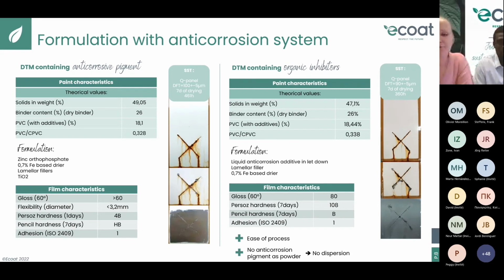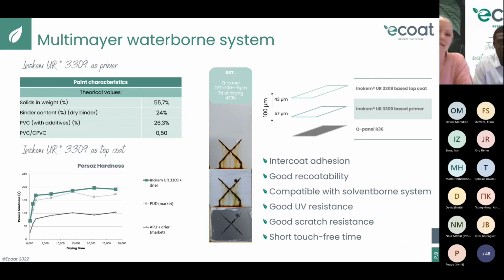These are for the direct to metal coating, but you can also use 3309 in a multi-layer system. Indeed, it is possible to use 3309 in primer or in top coat. Primer is a good option thanks to the corrosion protection we just saw, and it can be formulated to coat a variety of substrates. But 3309 also has a very good hardness development, as you can see in the graph here. It also has a short touch-free time, good UV resistance and good scratch resistance, which enable its use in